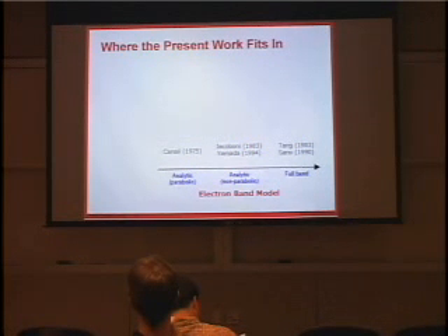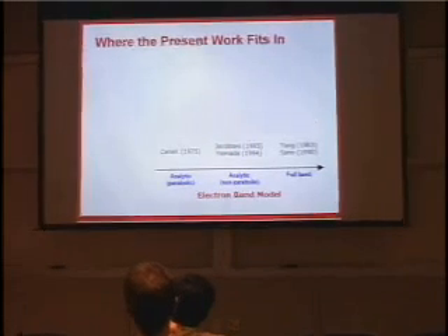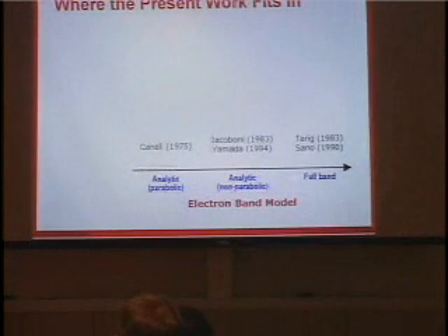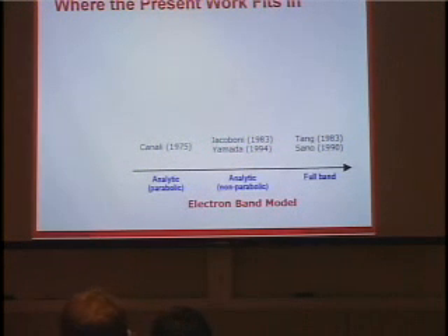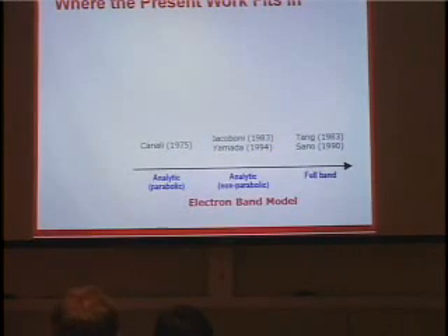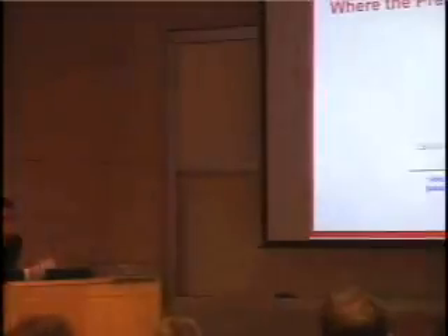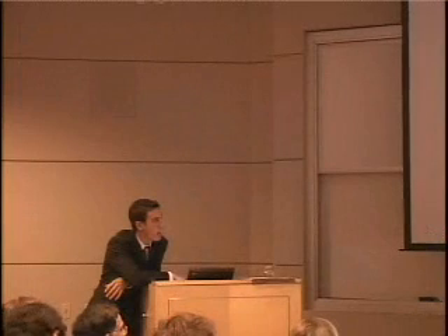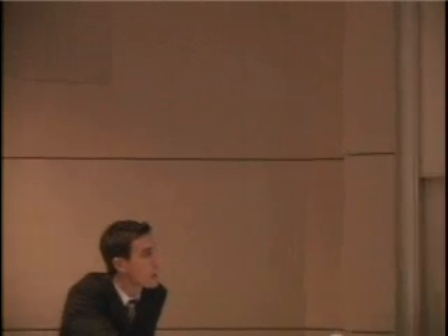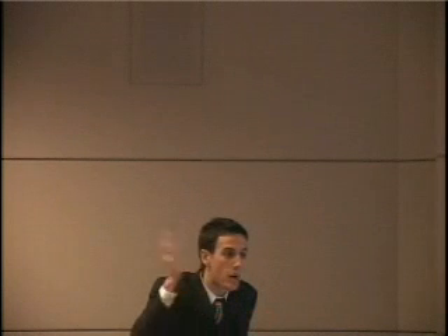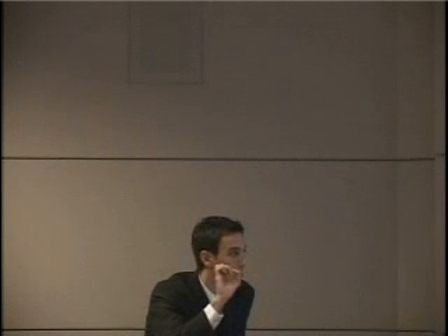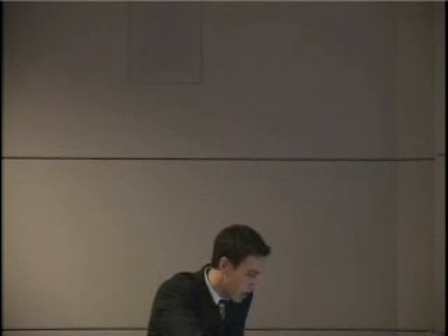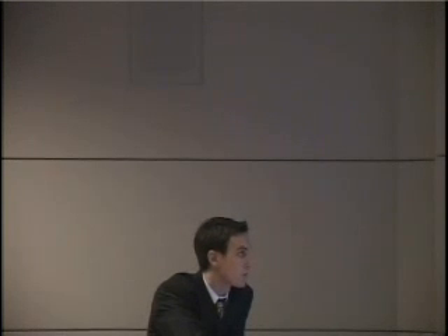Again, the two main ingredients are the electron band model, and there are varying degrees of sophistication for that. There are analytic bands, there's the non-parabolic approximation, which is the correction, and then people have gone into full band models for the past 20 years, actually. The only problem with full band codes is that they're very, very slow. You need to tabulate the entire energy band structure, and you need to look up where an electron is, compute its momentum, compute its energy, everything. It's a table lookup problem, so it's rather slow compared to an analytic description.